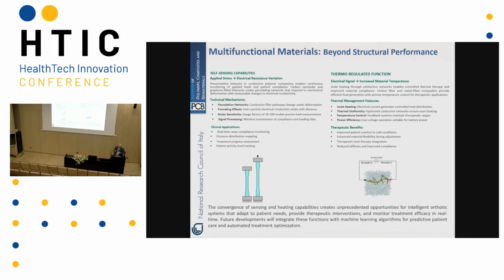Well, it's not a problem in some cases. For example, you can use this effect to obtain smart materials, for example for making self-sensing materials. In particular, when you apply a stress on this type of material, the stress is able to move or change the alignment of the filler inside the material. So you can change the electrical properties. So by following the electrical conductivity of this material during a mechanical test or during normal use, you can obtain continuous monitoring of the condition of the material, with important information on what happens to your items.